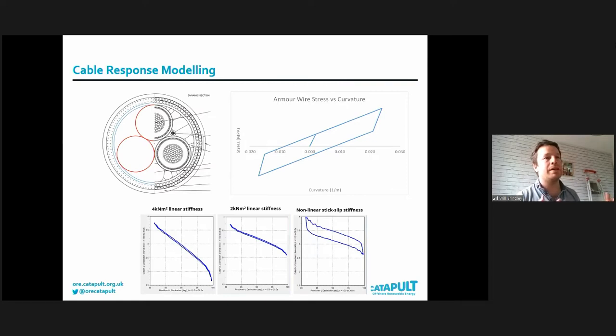And that's the non-linear stick-slip type stress-strain curve, where the armor wires, due to the helical nature when you tension up, but also due to the sheath shrinking when you form it over the cable, tend to stick through friction to the inner layer. And that gives you quite a stiff bending response. And then when you get over that frictional threshold and the armor wires start to slip, you get a lower bending stiffness. So that's quite important to the fatigue of the components.